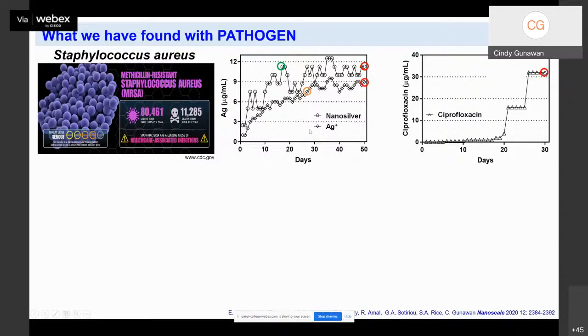We exposed the Staph aureus bacteria over 50 days of continuous prolonged exposure to silver nanoparticles through sequential passaging, or subculturing, every 24 hours. And you could see here that as we proceed with the prolonged exposure, the bacterium developed the ability to grow at progressively increasing nanosilver concentrations. The same thing was also observed for the ionic silver. In the course of 50 days of exposure, the bacterium was able to progressively proliferate even when subjected to progressively increasing concentrations of ionic silver. And of course, with ciprofloxacin, it is expected.